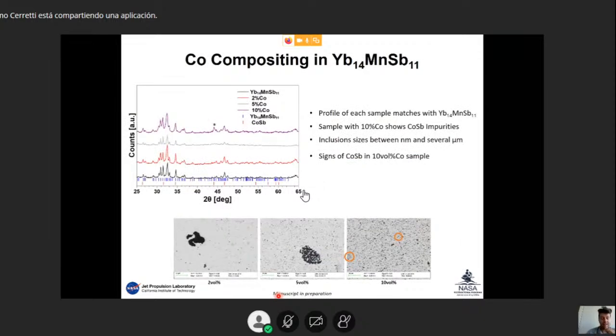I don't know if you have experience with X-rays or microscopy, but with these techniques we can understand the quality of the material and figure out if the material is exactly what we are looking for, and we can see that all the materials as prepared are exactly what we want. What we can deduce from here is that you can see the signal of the 14-1-11, which is the main phase, and we can see that the cobalt inclusions are pretty well dispersed inside. There's some small agglomeration, but all the inclusions are between a few nanometers and some micrometers in size.